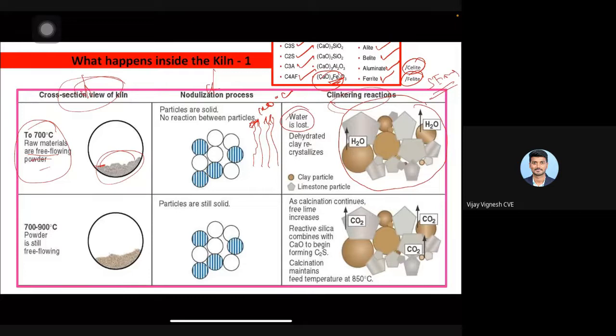Then dehydrated clay recrystallizes. So hydrated clay undergoes the dehydration process. We already have the clay, silica and so on. The water is lost from the clay, that is called dehydrated clay, which recrystallizes. So the clay changes in the crystalline process, right? So the structure will change. Here you can see the well-defined matter. Then CO2 is gone. The rounded particle represents the clay, then limestone. In the SEM, the limestone has a well-defined, angular shape. The clay particles are irregular, rounded in shape. The water tends to evaporate.